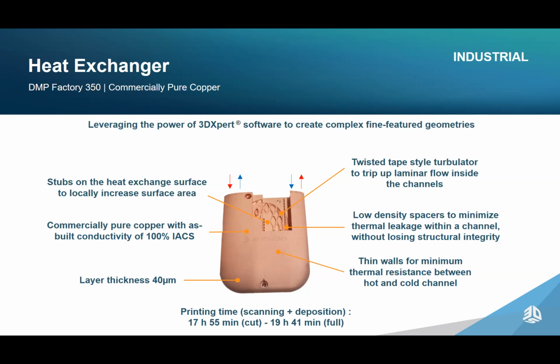You get parts that are almost completely dense coming out of the printer with 100% IACS, up to 103% IACS we've seen. So no heat treat is required. With heat treat, you just gain marginal advantage on IACS and density. So heat treat on commercially pure copper is not a requirement to get your full density. It's not like a binder over powder part where you have to go through a heat treat or a sinter to get to full density. And that's what some LPBF processes do require you to do, go through that heat treat to achieve final density. So luckily, we figured out a way to do this without that.